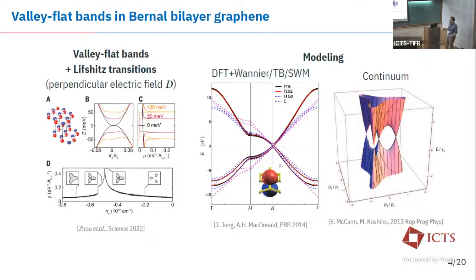Either you could start from an ab initio simulation, do some Wannier interpolation, or write down a tight binding model, or actually figure out a tight binding model given the orbital content of your material, and then come up with a tight binding Hamiltonian. Here you see only in this very tiny region around the K point you actually reach the Fermi level. Or you could go the other way, do a k.p expansion, write a continuum model, and truncate it in some parts around the K and K prime points.